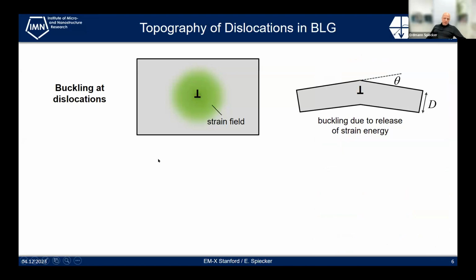So there are some peculiarities of dislocations in 2D materials or graphene. If you have a dislocation in the bulk material, you have, of course, a strain field like shown here for an edge dislocation. However, if you make the sample thinner and thinner, it starts to buckle in order to release part of the strain energy. And this has been studied many decades ago already by Amelinckx's group. There's a nice paper from Siems in 1962, and he derived a formula which is very similar to a small angle grain boundary formula, saying that the buckling angle is proportional to the Burgers vector divided by the thickness of the film.